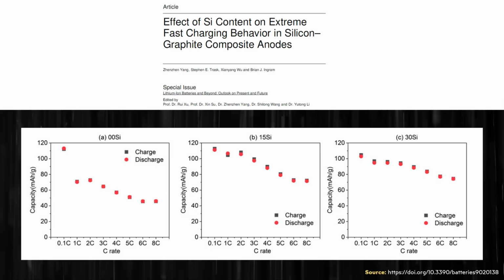With that being said, when it comes to fast charging performance, results were given in this research paper for fast charging tests that they did to a rate of all the way up to 8C, which, as a reminder, 8C means fully charging a battery in 7.5 minutes. So that's a very fast charge rate. And you can see here the results they have here based on the capacity loss and the charging speed there. And they have A, the battery with 0% silicon in the anode, B, 15% silicon, C, 30% silicon. And you can see when it comes to capacity retention, the batteries with added silicon actually have much better capacity retention even after charging at a very high rate of 8C.